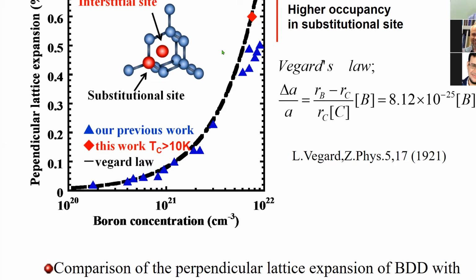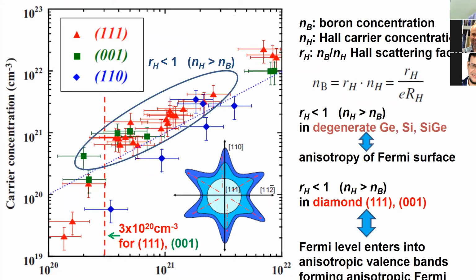Without prohibiting, without controlling the interstitial site, if we can make a substitutional site, then we get better quality diamond. This is one very interesting picture, because we can also get carrier concentration as a function of the boron concentration.